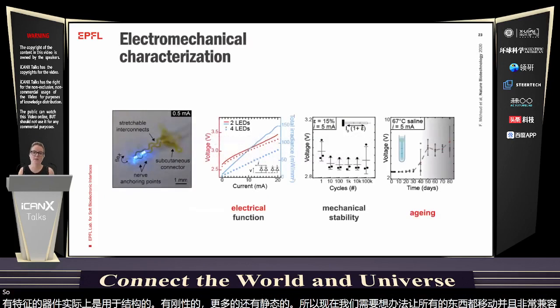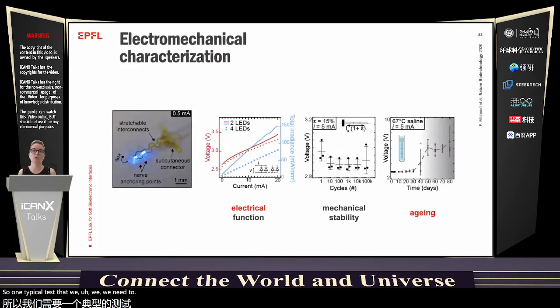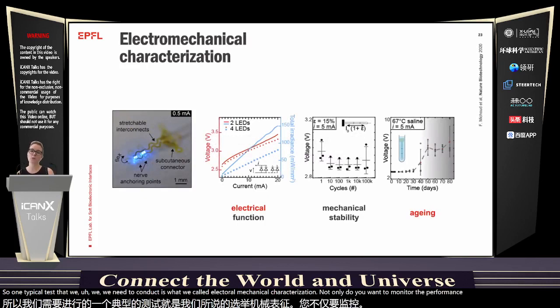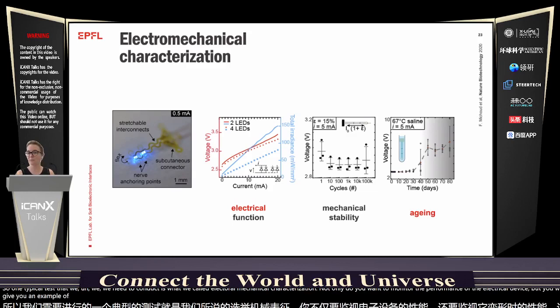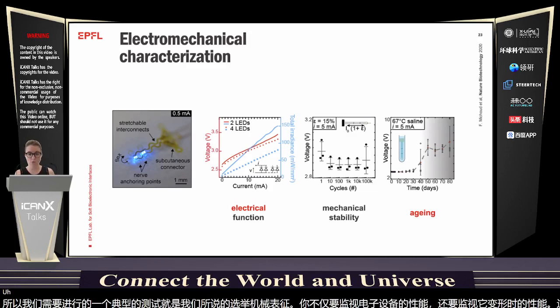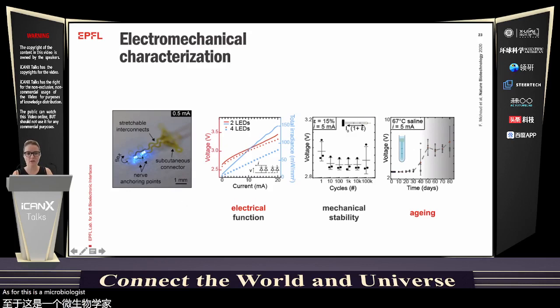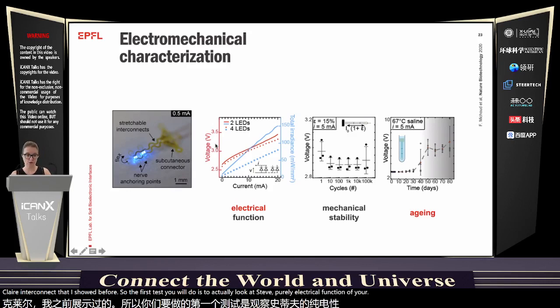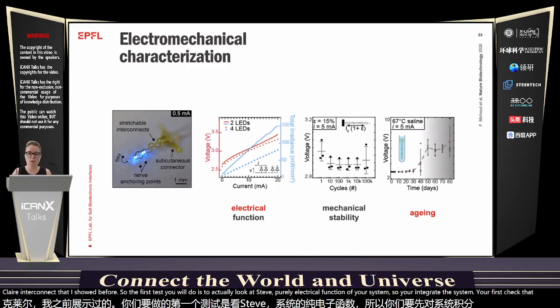So one typical test that we need to conduct is what we call electromechanical characterization. Not only do you want to monitor the performance of the electrical device, but you want to monitor its performance while it's being deformed. And here I give you an example of typical tests we conduct for micro LEDs that are integrated with the serpentine interconnect that I showed before. The first test is to look at the purely electrical function of your system. You integrate the system, and you first check that the electrical continuity and the performance of the device are what you expected.